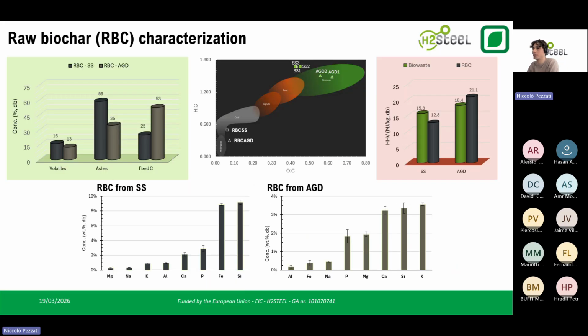So the two biochars that were produced, as I have just described, were also characterized. And here I want to draw attention to the key aspects of the slow pyrolysis outputs. So first of all, the thermal treatment allows to reduce the volatile matter in the solids, going below 20% threshold, so we can eventually see a 16% volatile matter content in the raw biochar from the sewage sludge, and a 13% volatile content in the raw biochar from the agricultural digestate.